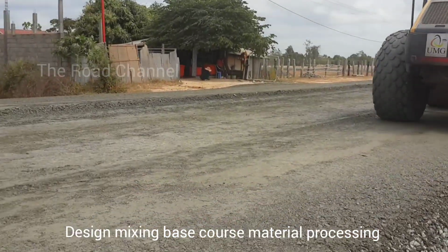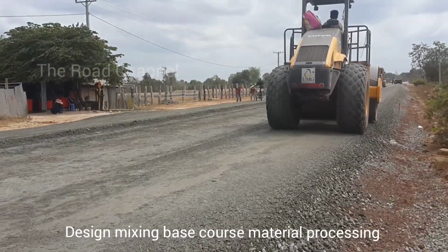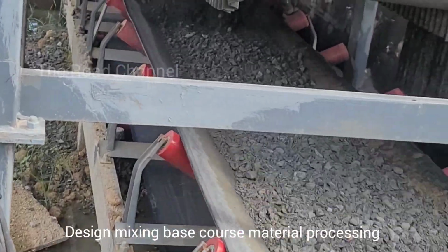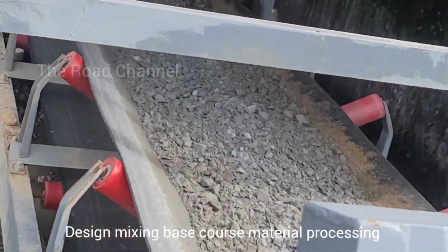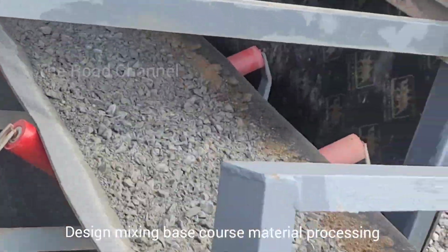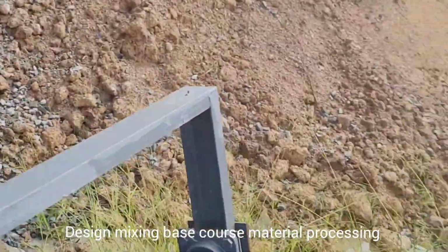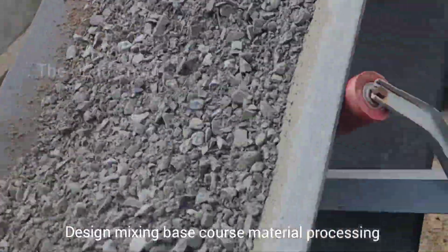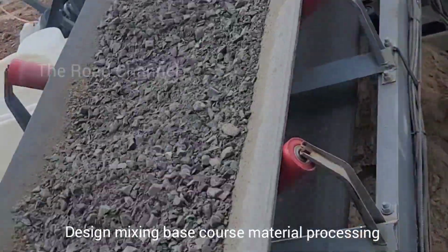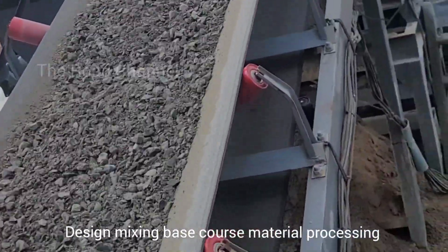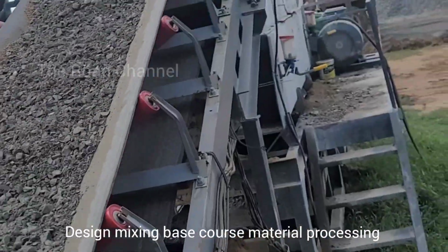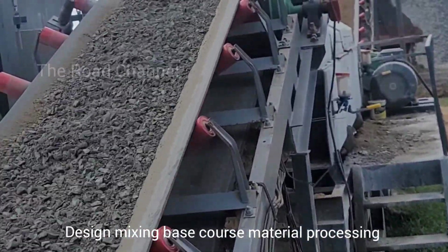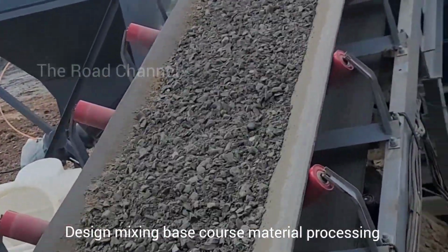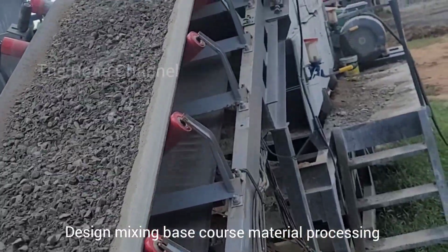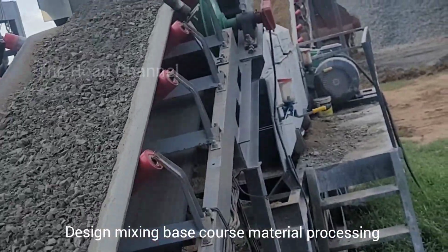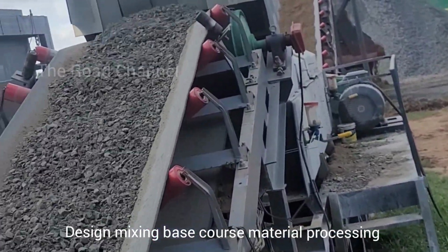Tools and software: pavement design software like PavementME Design, formerly AASHTOWare, can assist in modeling and optimizing the mix design and pavement structure based on inputs like traffic load and material properties. Example of proportions: for a base course mix, a combination might be 70% coarse aggregate, 20 mm to 5 mm crushed stone, and 30% fine aggregate, sand and fines. Water is added to achieve optimal moisture content for compaction, typically 5 to 8%.